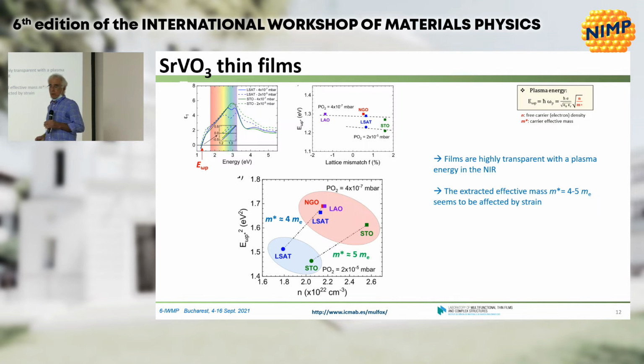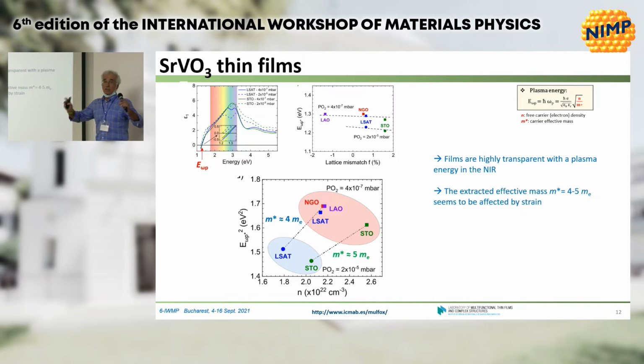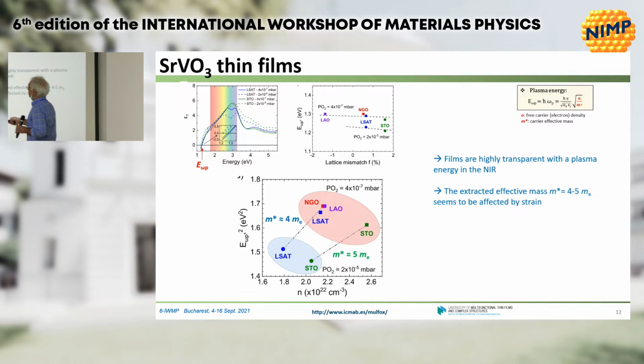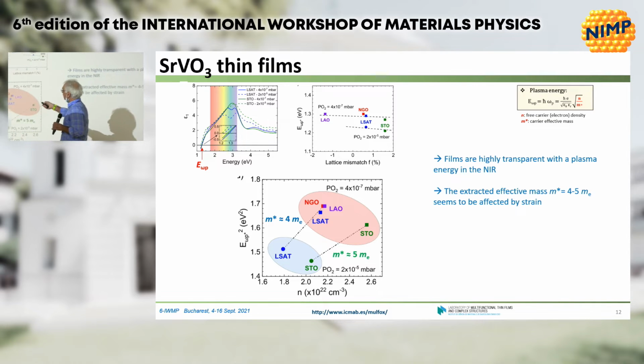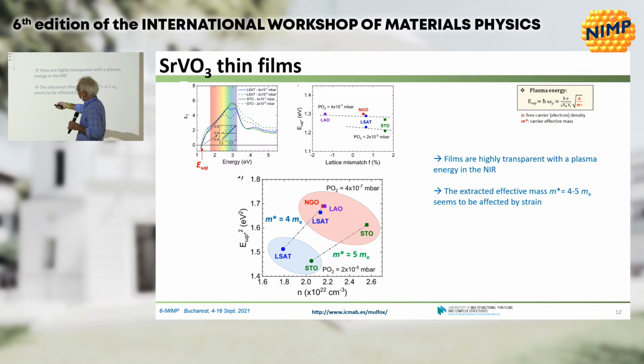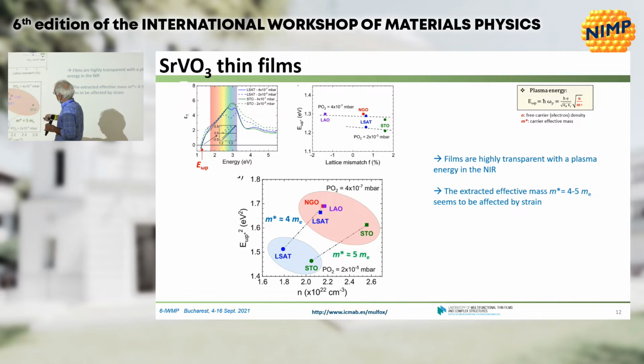Now an important point, what about the plasma frequency? That was the first hallmark. Here is the real part of the permittivity versus the energy for different films grown on different substrates and at different temperatures, and you see that they cross zero somewhere here. And this is a fingerprint of the plasma frequency. Here you have a zoom of this crossing point.